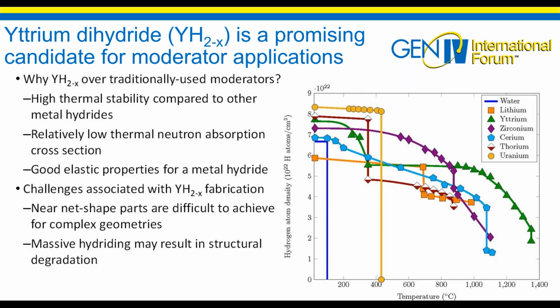Yttrium dihydride also has thermal stability compared to other metal hydrides, a relatively low thermal neutron absorption cross-section, and good elastic properties. There are some challenges associated with yttrium hydride fabrication in the fact that near-net-shaped parts are difficult to achieve for complex geometries, and large amounts of hydriding may result in structural degradation. In particular, we have some issues with cracking on occasion, but there are multiple fabrication techniques and advancements that have been made to reduce these concerns.